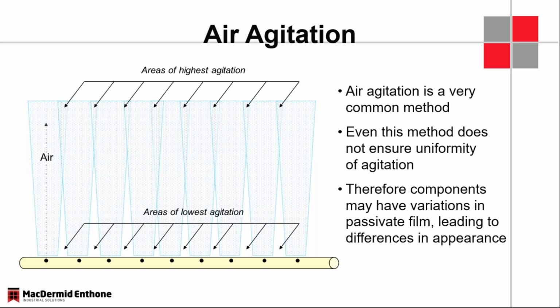Before we started doing that, the bottom part of the rack looked completely different than the top part of the rack. We did the up and down every 45 seconds, and we got a uniform looking appearance across the entire rack envelope. Just because we had good air agitation, the customer kept telling me, how do you get more air? This is the best air agitation I've ever seen. I said, let's move it up and down and see if we can, and that worked. So air agitation is that important.